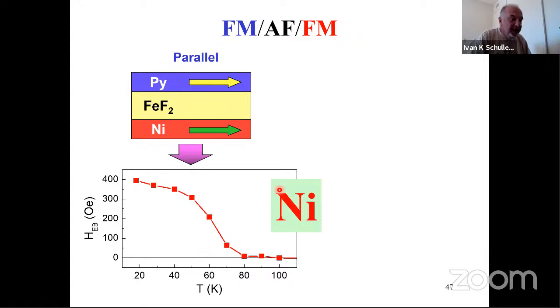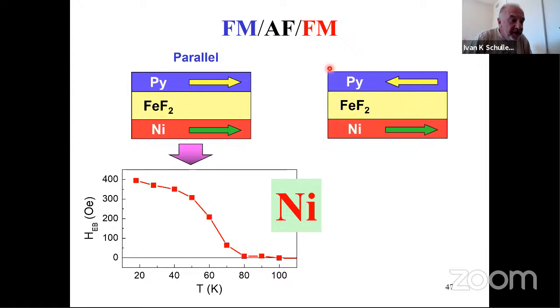Now I will reverse the magnetic moment of the top layer. If you want to ask me how I do that, I can explain it, but if not, believe me, I can do that. So nothing should happen, of course. What happens here? I reverse the magnetic moment of the permalloy with respect to the nickel. Now notice the nickel is very far away, 200 nanometers away. It's a very long distance away from that material. And if I do that,